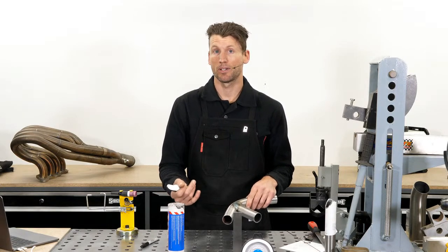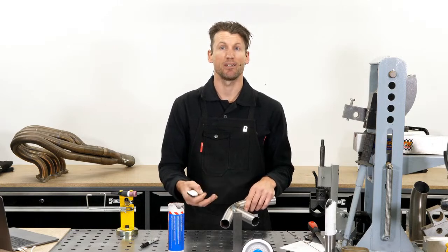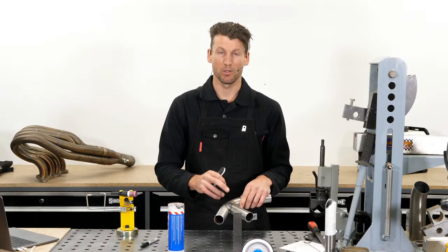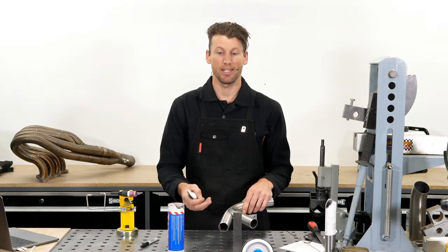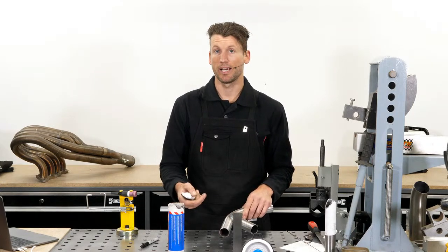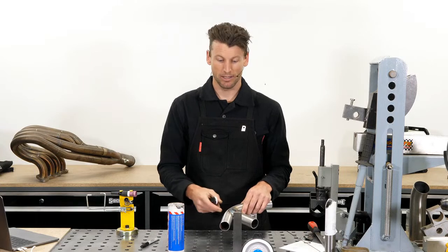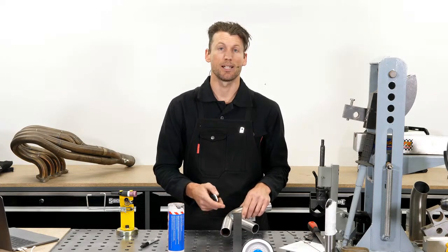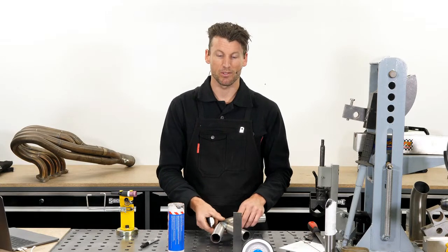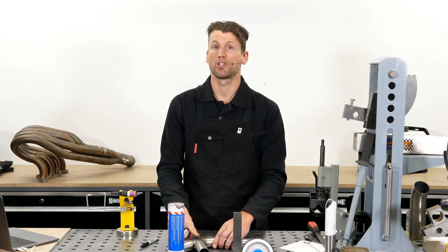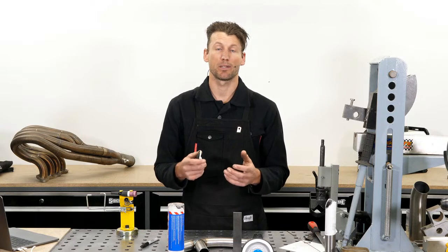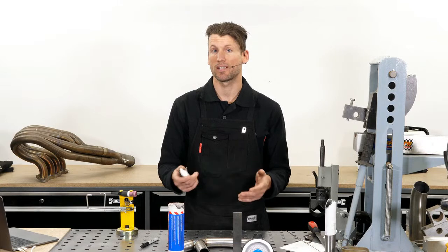You can MIG weld it, which means a more aggressive input of heat. But when you TIG weld something, you create less heat, and that's why for chromoly, you must not MIG weld chromoly, because this fast input of heat shocks the heat affected zone around the weld and can cause it to become brittle. And on a lot of drag cars, you see them flexing a lot on the start line.